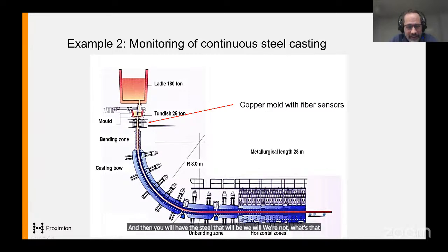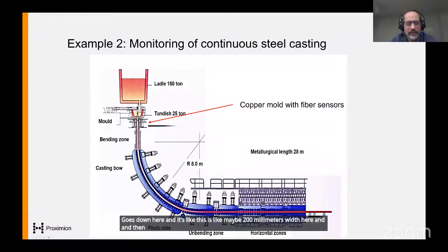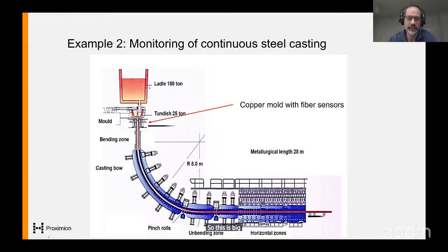It will solidify here, at least at the surface, with the steel coming out at a rate of 1 to 3 meters per minute, and then it goes down here. This is maybe 200 millimeters in width, and in the depth direction, maybe up to 2 meters. So this is big, but a critical stage here is the solidification, because that can affect the